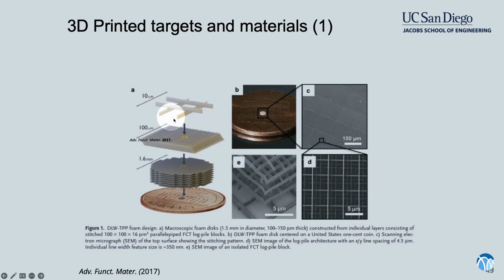The unit cell here is this 4-bar truss structure. Then you take that 4-bar truss structure with less than a micron length scale. This is a 5-micron bar here, and this is the top view of this. So it's a nanostructured, microstructured truss. And you take that and you repeatedly print that unit cell, and you repeatedly print it again. And so it's a very small target. Here's a picture on a US penny. And they shot this material in some high energy lasers, in Omega and the NIF. And what you see is that the change in densities drives plasma pistons such that you can get the pressures that you're looking for.